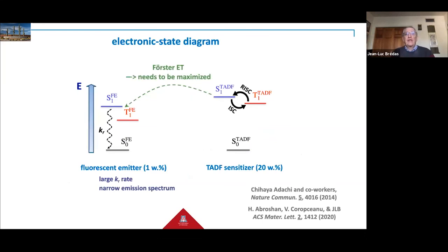And if we look at the electronic state diagram, on the one hand, we have the TADF sensitizers, on the other hand, the fluorescent emitters. We want to maximize the rate of energy transfer from the singlet excitons on the sensitizers to the singlet states of the fluorescent emitter, but then we also want to prevent the Dexter energy transfer from triplet to triplet, because here those triplets would be wasted.